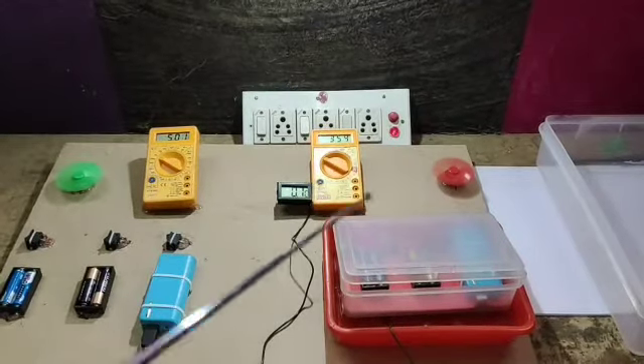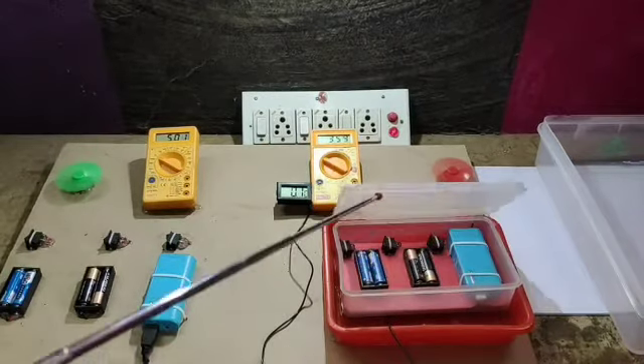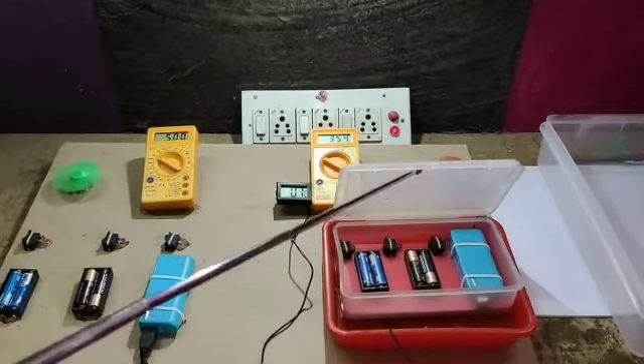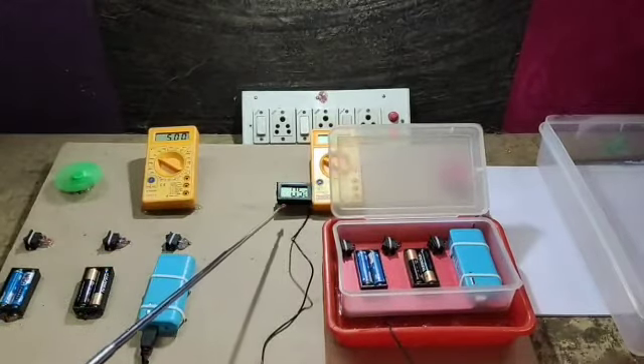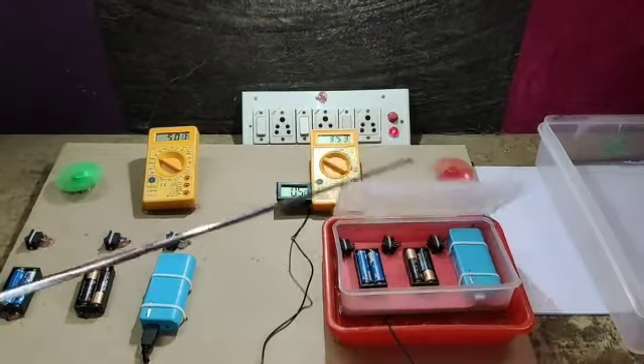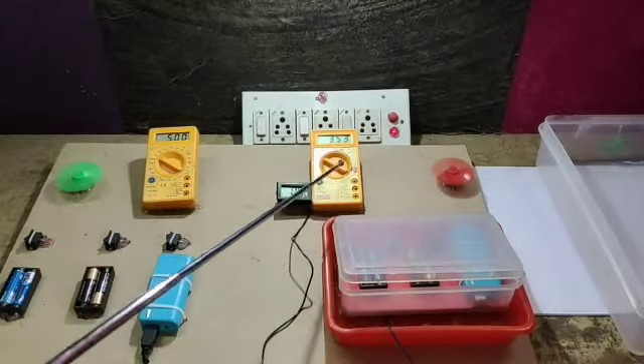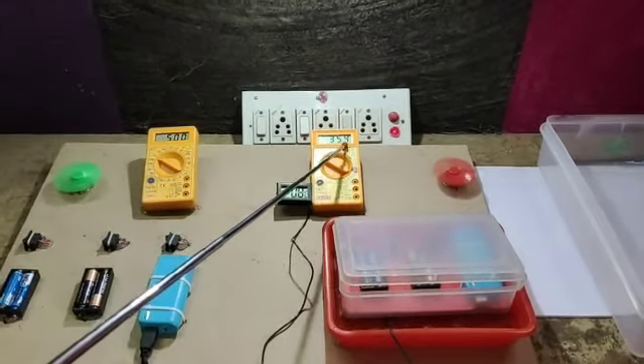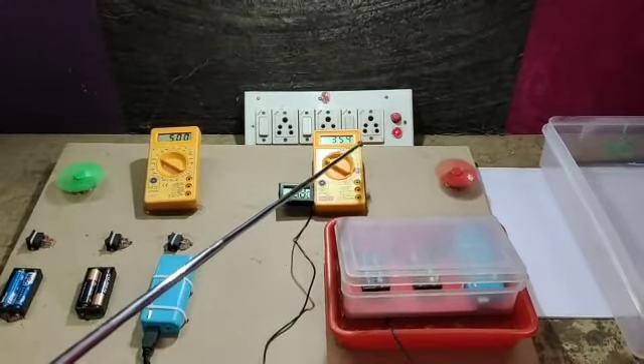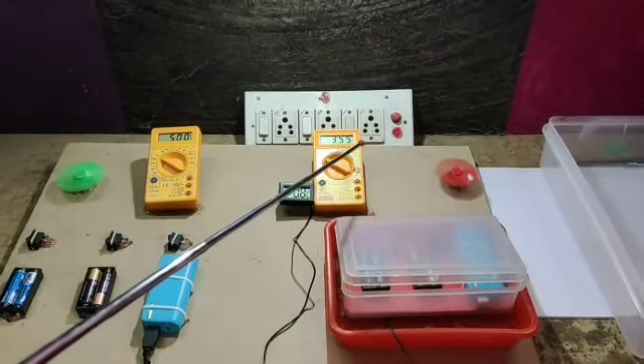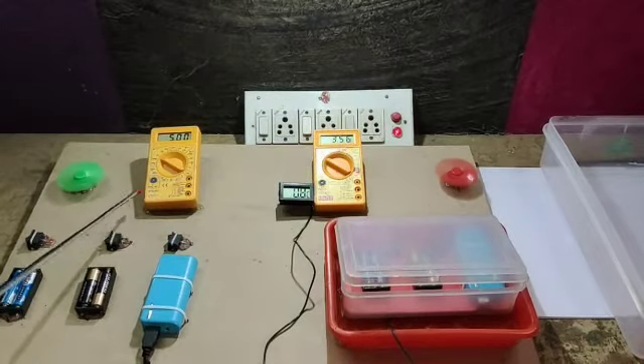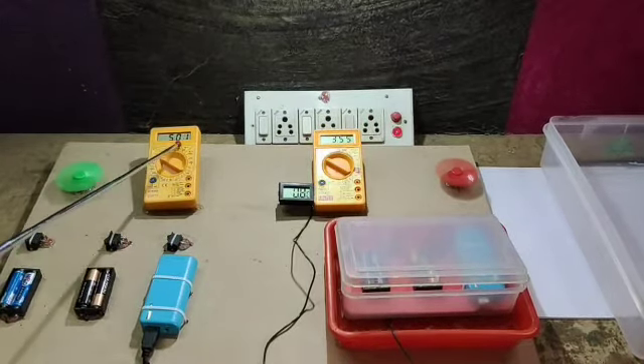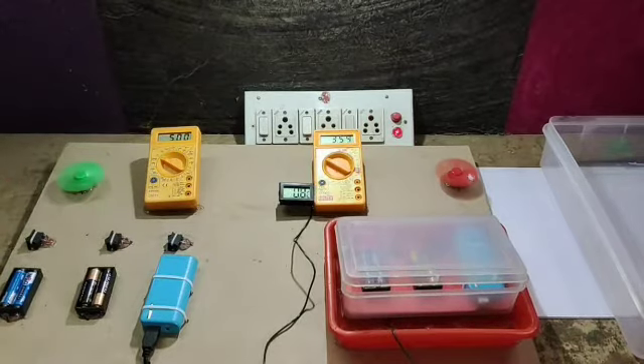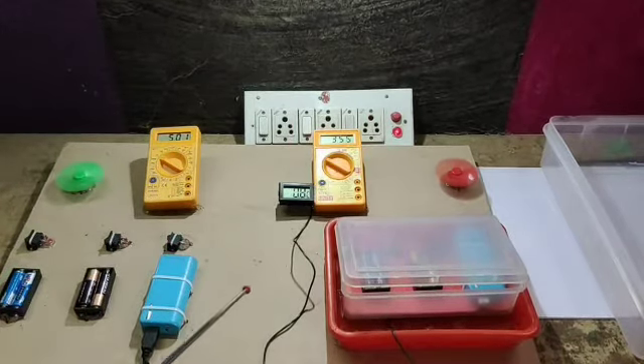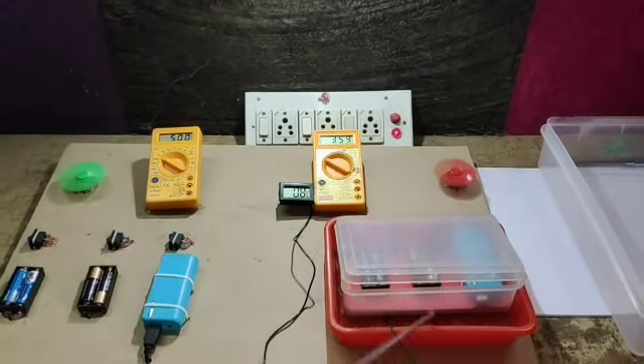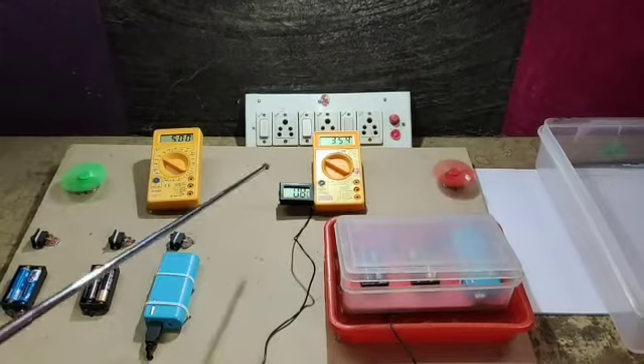You can see the difference. Current temperature in set B is 0.5 degree and you can see the voltage of it is 3.54. Here we can see the voltage reduction by 1.45 volt. And in set A the voltage is 5. Still it remains 5. This is maintained at normal room temperature. This is maintained at cold temperature, at 0.8 degrees centigrade.